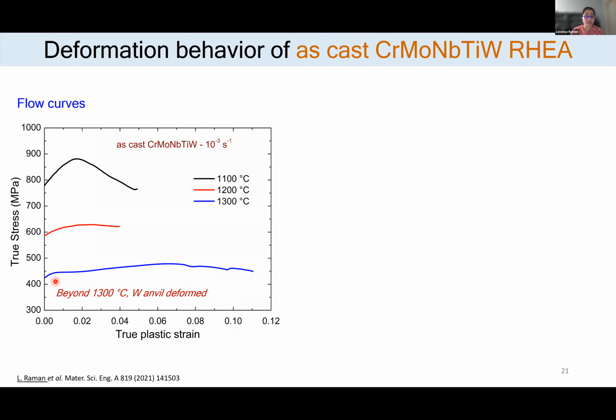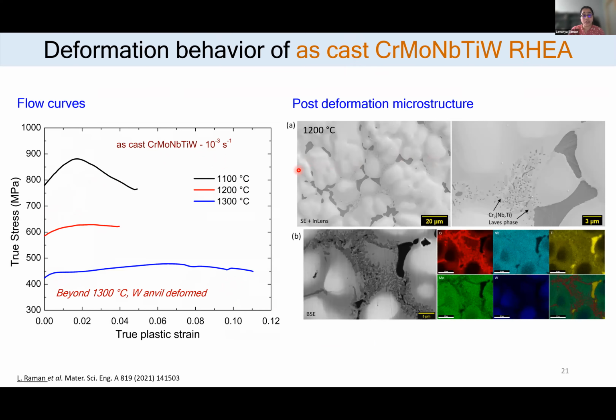Now coming to the cast HEA, the flow curve of the cast HEA at low strain rate is shown in this figure. We can see that they have very high strength compared to our mechanically alloyed counterpart. And the deformed microstructure of the alloy at 1200 is something like this, where we can see the precipitation of this Laves phase in the interdendritic regions. This Laves phase was confirmed to be Cr, Nb and titanium rich through the elemental mapping analysis. The as-cast alloy in the synthesized condition had only a single phase BCC. Now after deformation, we have the formation of Laves phase.